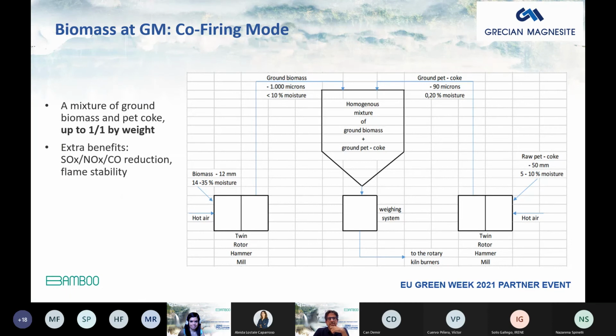How are we utilizing this biomass at Grecian Magnesite? We combust it directly in a co-firing mode. We produce a homogeneous mix of ground biomass and ground pet coke. We are striving to increase this up to 1:1 by weight, and then feed this to the rotary kiln burners.